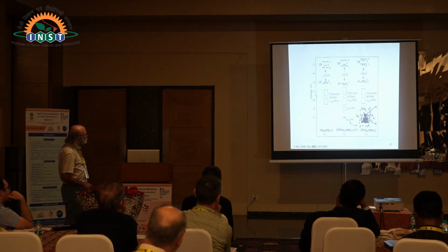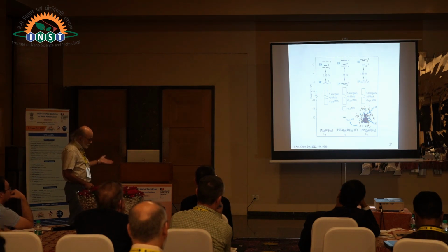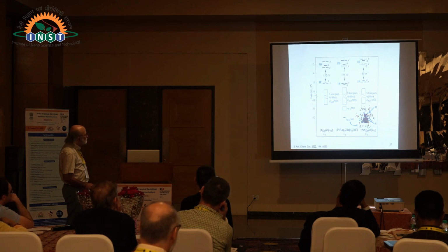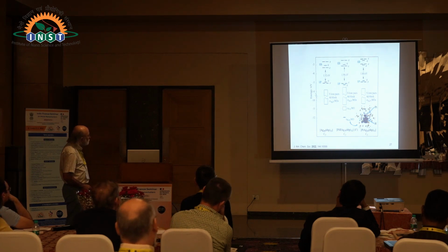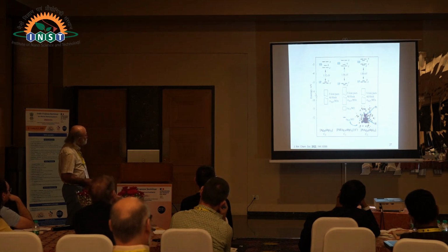This is exemplified by these three MO diagrams. We have the hydrogen-encapsulated species over there, and on both sides we have related systems which are isoelectronic but don't have any encapsulated hydrogen. They have basically the same electronic structure. The only difference is that this compound has a low-lying sigma Pt-H bonding molecular orbital, which is mainly made of a dz2-Pt contribution.